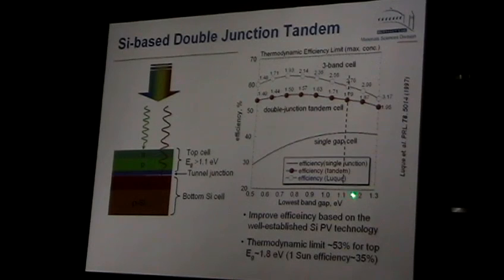So silicon is 1.1, this is the low energy gap, and this is let's say 1.8. So the problem is nothing much for silicon. Gallium indium nitride you can do because it doesn't care; it can be low quality. However, if you want to do any other 3-5 material, it's always lattice mismatch.